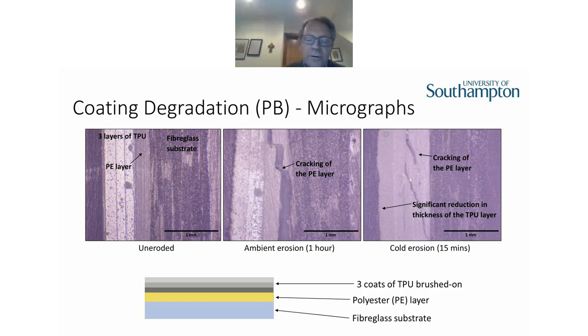Slightly, you could argue it's 45 degrees, a slightly different type of crack system, but that's only after 15 minutes. So it would appear that the polyester, and it's nowhere near its glass transition or anything, would appear to be subject to cracking, which is undesirable because, as you say, it undermines the polyurethane, and you can see there's a huge amount of erosion on the top surface of the polyurethane.